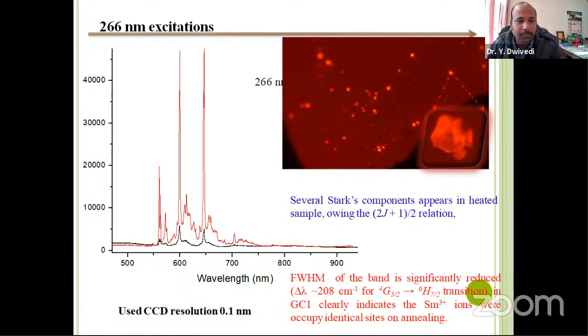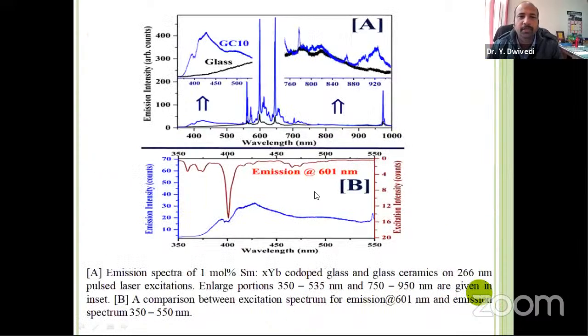So this is a PL spectrum, just for comparison purposes - you can see the black represents the glass emission spectrum, and these sharper lines are really surprising, this is the advantage of glass ceramic. You can see the bandwidth is around 2 to 3 nanometers only, so it may act for biolabeling purposes. This is the confocal microscope image at 405 nanometers - you can see the very bright spots somewhere, which represent the samarium emission.